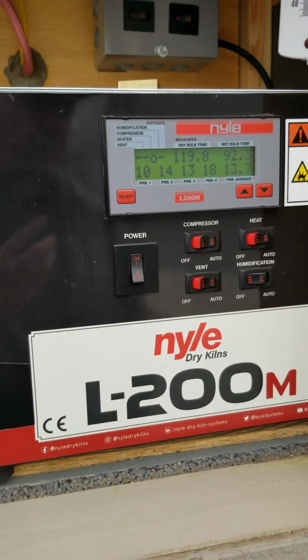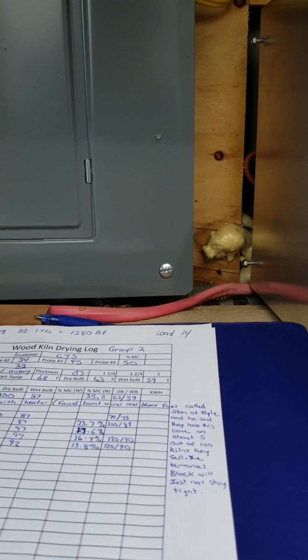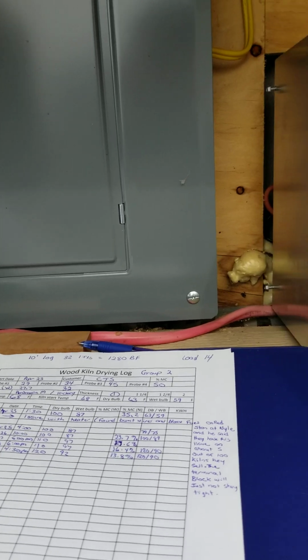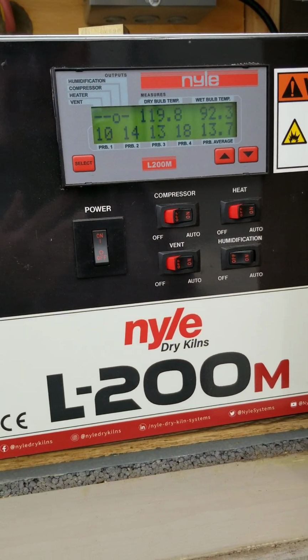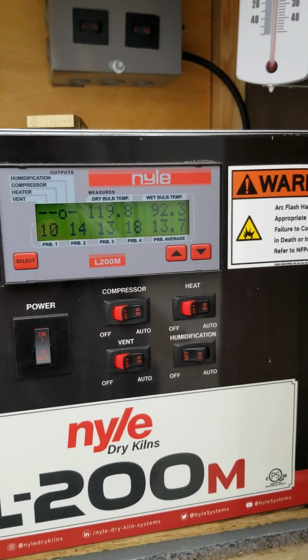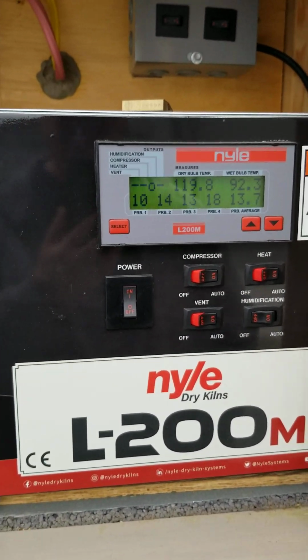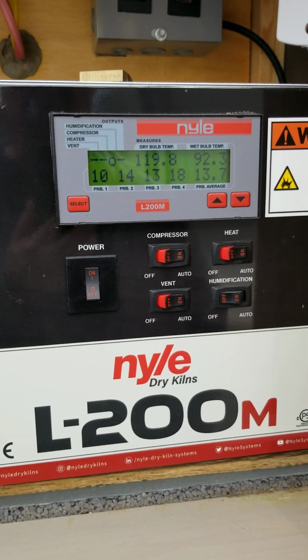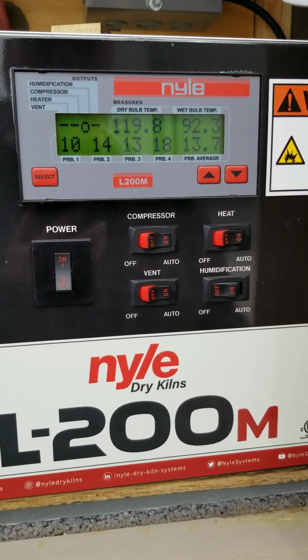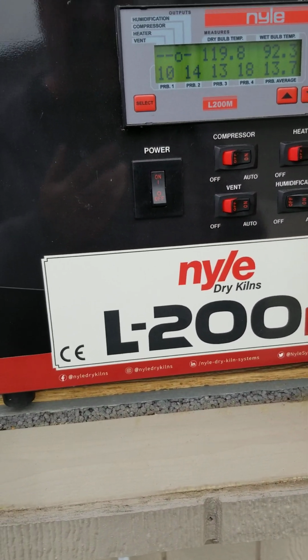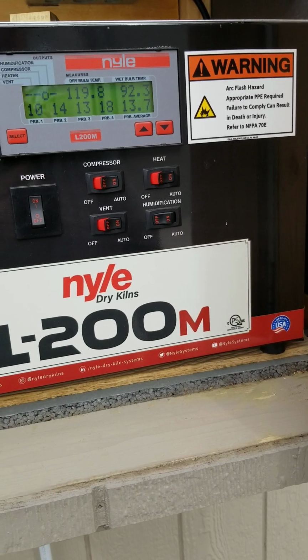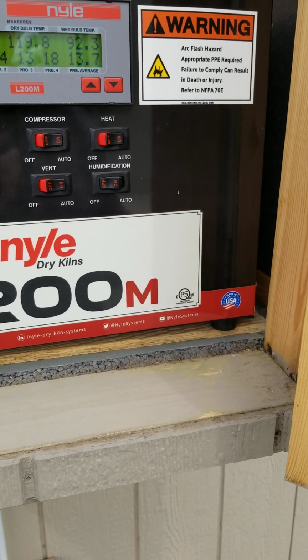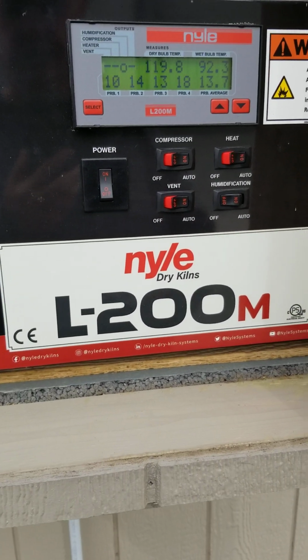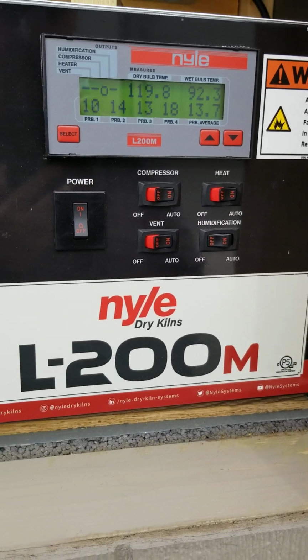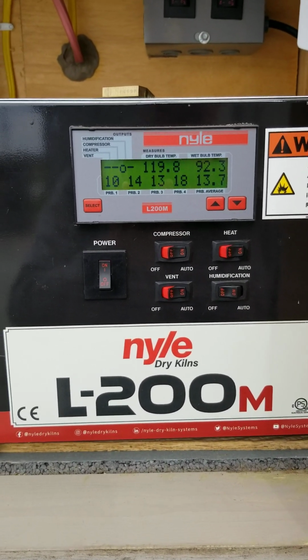Yeah, right now this load should be done probably in another 2 or 3 days, and then we will go through a sterilization process, and we'll crank this temperature up to 150 degrees, and we'll leave that for about 24 hours to make sure the wood is good and sterilized, meaning we're trying to kill any of the bug larvae in the wood. So any little critters that bored in there, if the internal wood is 130 degrees or over for at least 30 minutes, that should kill any larvae in the wood. So that's kind of the standard for sterilization.